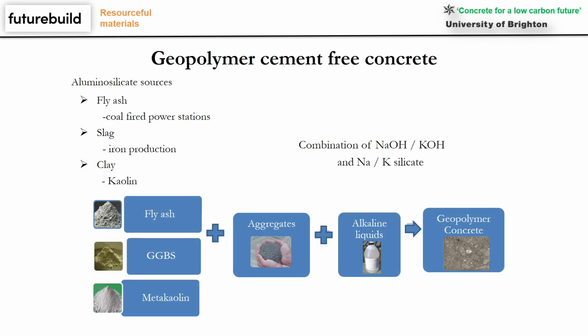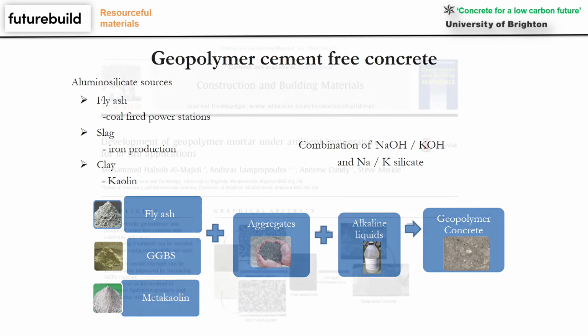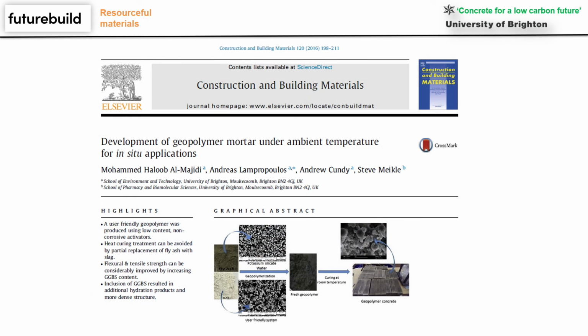How do we make geopolymer concrete? We use waste materials, normally fly ash, GGBS, kaolin as well. We can use aggregates, but we also need to do the activation. So we need to add some chemicals. We normally use sodium hydroxide and sodium silicate or potassium. We need to do the activation in order to provide the strength. So we have the waste materials, aggregates, the activators, and we can have the geopolymer concrete. I will present 2 or 3 papers of our recent findings on geopolymer concrete and on the use of this material for structural applications. This one is focused on how to use concrete for in situ applications.